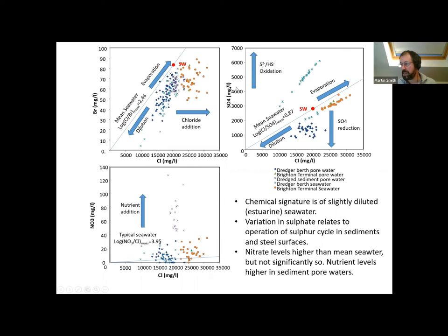If we look at chloride against sulfate, we see reduction of sulfate compared to normal seawater. So sulfate reduction going on, particularly in pore water samples, and sulfur oxidation, presumably against the steel surface.